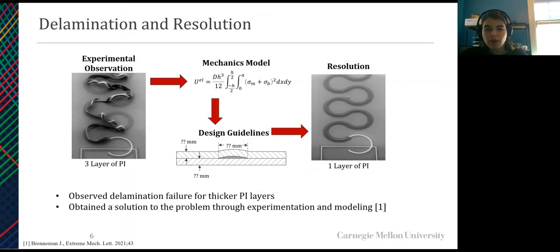However, thicker layers of polyimide resulted in higher instances of delamination during the final curing stage of the top layer of polyimide. This undesirable behavior is a result of vapor-driven delamination, where the absorbed moisture in the previously cured polyimide is able to vaporize at the heterogeneous silver interface and provide energy for delamination. We have published work on this understanding, and it is cited here as well.